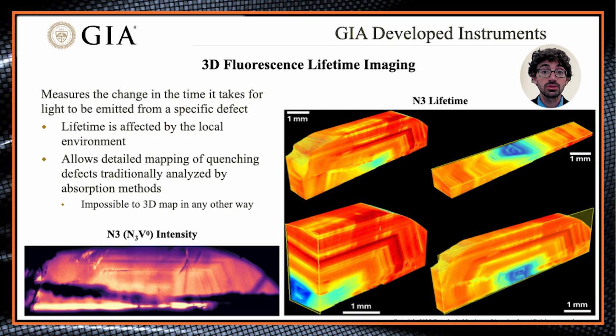A significantly less measured property of photoluminescence is its lifetime, which you can think of as the time it takes for light to be emitted from the defect after excitation from the light source. This is useful as it can be used to evaluate the concentration of three nitrogen atoms in the diamond, something typically only possible with absorption at relatively high concentrations. Any facility which has this capability typically can perform it on bulk samples with no localization, with the rarer ability to measure these as localized points. However, at GIA, we have developed the ability to measure this lifetime property in a three-dimensional volume to create localized 3D maps of this concentration.